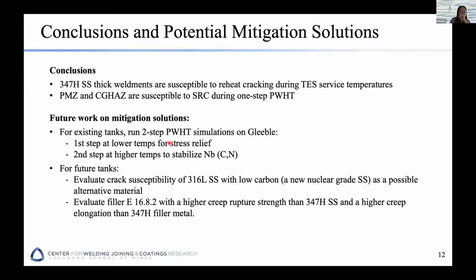So there are two solutions. First, we can run a two-step post-weld heat treatment, because if you do only one step, eventually at whatever temperature you put it under, it will crack, just a matter of time, okay? So we run this two-step post-weld heat treatment. The first step is to relieve the stress, and in the second step, we want to stabilize the niobium carbon nitrides, so they will not form those preferential coarse carbides at the grain boundaries and fine carbides inside of the grains, okay?